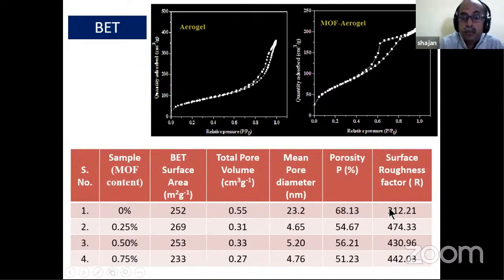And you can see the surface roughness and the pore diameter. The mean pore diameter, you can see, is 23.2. As you have seen earlier, the mean diameter is very high, whereas it is being reduced. It is around 5 nanometers. One thing you should be very careful about, because for solar cell applications, your pore diameter should be around 5 to 20 nanometers. Otherwise, it won't work for this.